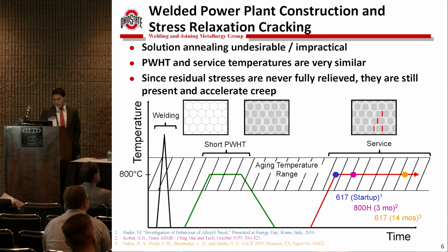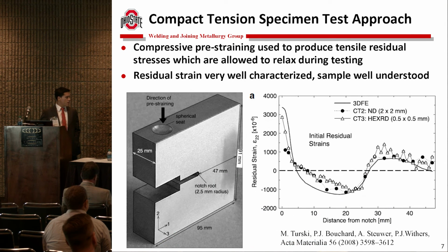As a creep-based phenomenon, there are different tests we've tried to do, especially in the Gleeble. But today I want to talk about a test which moves away from the Gleeble, and it's based on a compact tension sample. These authors, Mark Turski was a PhD student under Professor Withers, and he was investigating similar cracking phenomena in 316H stainless steel. I really liked his testing approach because it's entirely self-restrained. The loading is dependent entirely on the material.